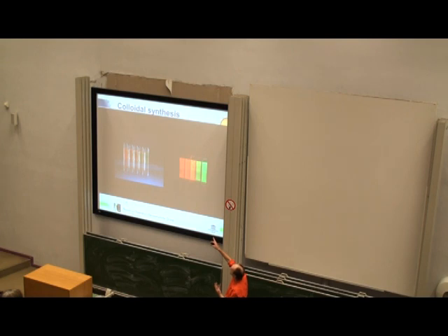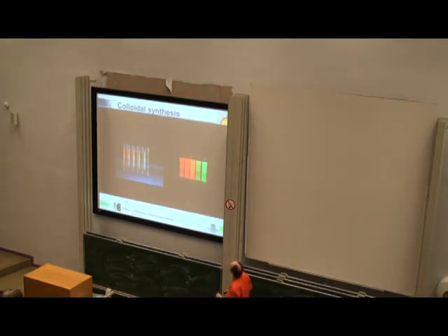And during the reaction, at specific times, we have taken aliquots. And at the end of the movie, you see these aliquots. At the left, it's just in transmission. You see their light absorption. Again, this color shift, yellow at the left, the smallest nanocrystals, towards the red at the right, the largest nanocrystals.